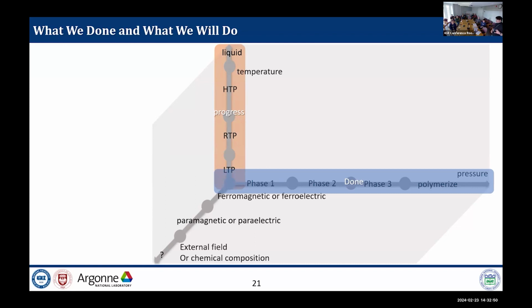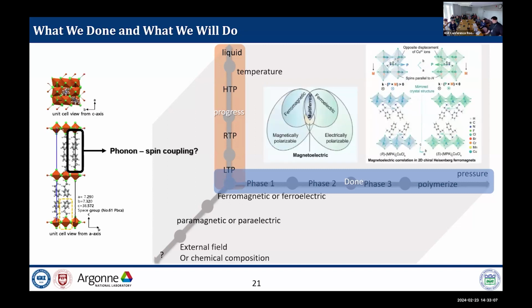I think when we fill up this phase diagram in the pressure and temperature plane, we can understand the PA-based quasi two-dimensional system, specifically the coupling of the metal halide octahedra and the organic cation, the organic molecule. We expect large spin-phonon coupling or large magnetoelectric properties arising from the chirality of the organic molecule. It can be combined with spin-phonon coupling or magnetoelectric properties like this figure.